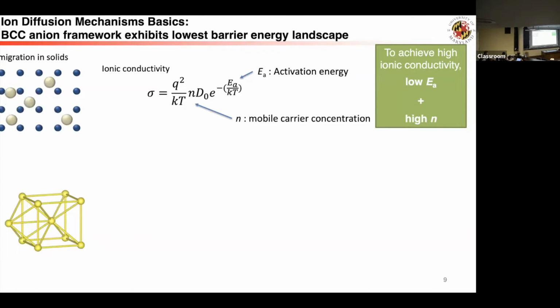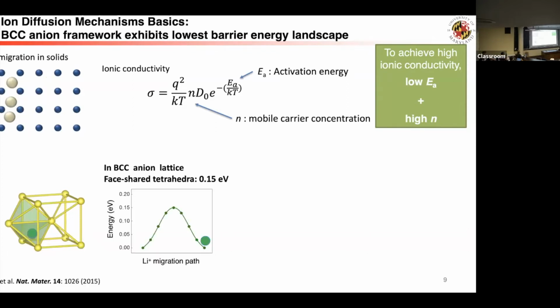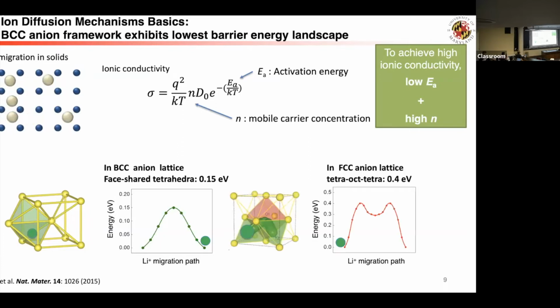They move through this path, and the barrier is about 0.15 eV, which is a very low migration barrier. But if you have FCC, close-packed anion packing, which is very common, then they go through these paths, and that gives you about a 0.4 eV barrier. Entering this into the exponential here, at room temperature that difference is about 4 orders of magnitude. So that's a very significant difference.